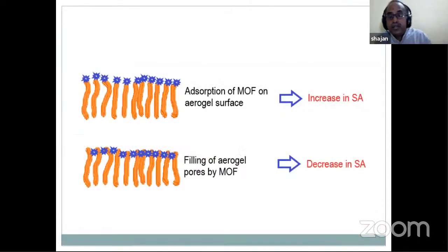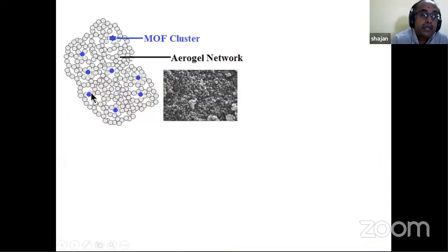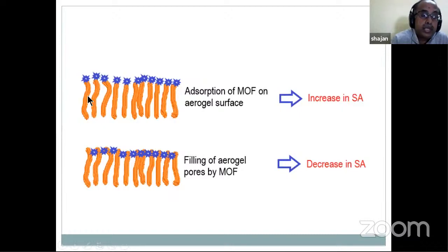Now, why the surface area is decreasing in certain cases and increasing in certain cases, you can see that depends upon how the MOF is adsorbed to the surface. Like this, this is the pore of the aerogel. And if the MOF is sitting on the surface, then automatically your surface area is increasing.